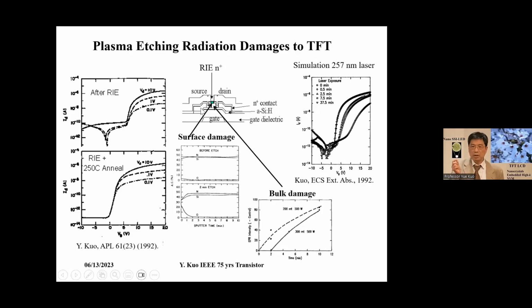In the IC, plasma damage usually comes from thin gate dielectric breakdown during plasma charge neutralization. But for TFT, because the gate dielectric is very thick, that phenomenon doesn't happen. But the radiation damage happens. And this can even be confirmed with a good transistor. We shine UV light, for example an argon laser with double frequency, on the TFT. You can see the performance is exactly like after plasma etching damage. Then after that damage, we can anneal to repair it to the original condition, a good transistor.